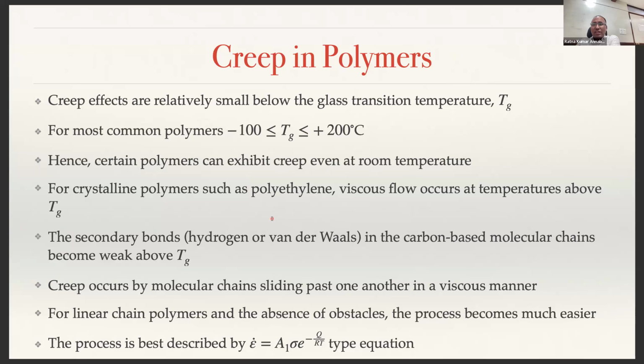And similarly, we have heard of creep in polymers. It may actually happen at room temperature for several polymeric materials. That is because their homologous temperature will be very close to room temperature, and hence creep effects are usually apparent. So when we talk about polymers, we define this so-called high temperature as the glass transition temperature. For most materials, the glass transition temperature will be as low as -100 to as high as 200 degrees Celsius. So that is why you can see the creep even at room temperature for several materials.